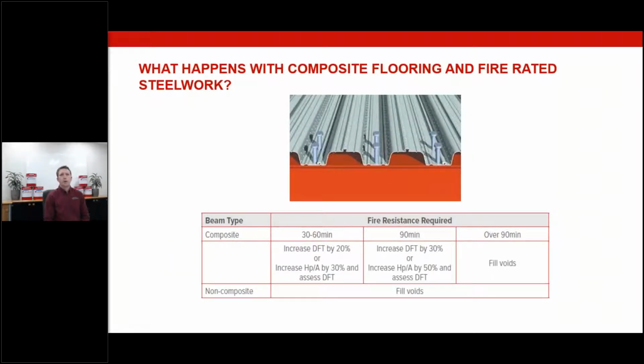What happens with composite flooring and fire-rated steelwork? It's commonly known as comflor or tray deck. You can see an image above the table there. Anything from 30 and 60 minutes, the coating manufacturers will increase the dry film thickness of a common three-sided beam by 20% to compensate for that particular keyhole shape that you've got sitting on top of the beam. Once you go to 90 minutes, that is increased by 30%. Once you go anything over 90 minutes, you've got to fill those voids with fireproof blocking.